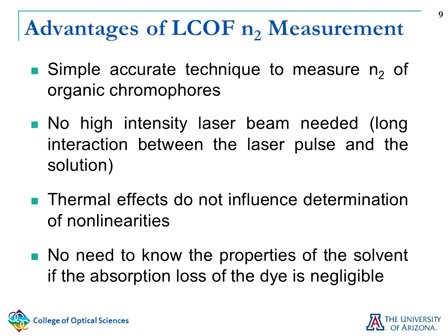The good point about this introduced method is that it's very simple and accurate, and the liquid core optical fiber that we use for this work is about 0.5 meter, so we have a long interaction between the laser pulse and the solution. For that reason, we wouldn't need any high intensity laser beam. And because we don't need a high intensity laser beam, the thermal effects can be ignored, as well as some higher order nonlinearities.